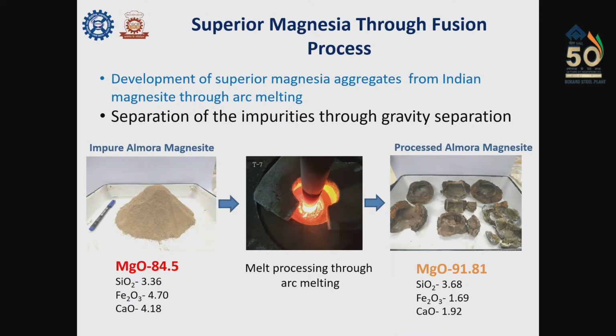And another approach is where we use an arc melting probe. We know that the impurities Fe2O3 and titania have a higher density. So if we can convert this Fe2O3 either to ferrosilicon or to metallic iron, those will be separated through gravity separation. So we did a preliminary study with Almora magnesite, where the magnesia content was 84.5%, and we have reached a magnesia content of almost 92%. There is a long way to go to reach 97% or more, but this can be done through this arc melting process with proper selection of the parameters.